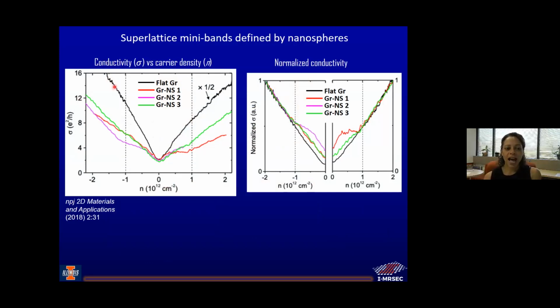For the black one here is the flat graphene. Okay, so that's graphene, we don't expect any additional dips. And then the green, the magenta, and the red are three different devices that are on top of nanospheres. Okay, so you want reproducibility here. So we have three different devices on top of nanospheres and measure their conductance.